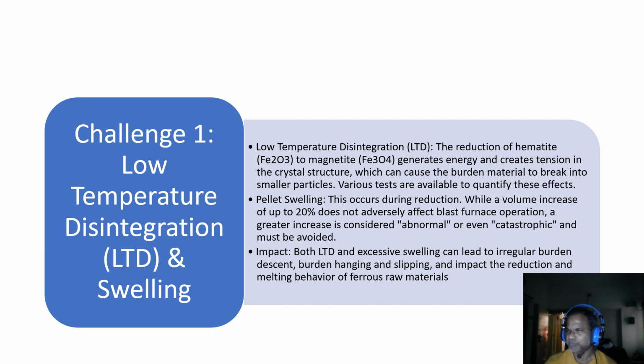Various tests are available to quantify this. Closely related is pellet swelling, which also occurs during the reduction. While a volume increase of up to 20% is generally acceptable and doesn't significantly harm the furnace operation, a greater increase is considered abnormal or even catastrophic and must be avoided. The significant impact of both LTD and excessive swelling is on the smooth and regular descent of the burden within the furnace. They can lead to issues like burden hanging and slipping, which directly interfere with the efficient reduction and melting of the ferrous raw material.